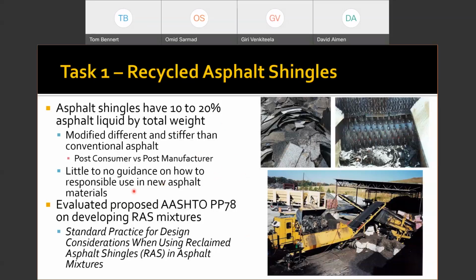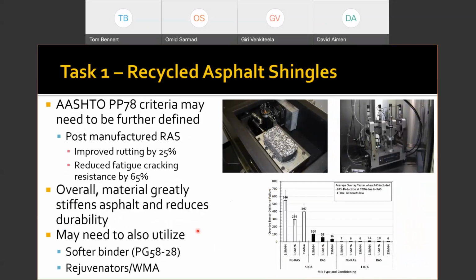And so we went back, took a look, did a research study looking at this proposed AASHTO method that they were proposing. And again, the idea here is, can we actually responsibly use recycled asphalt shingles in new hot mix asphalt? And we looked at a surface mix, we looked at a base course mix, could we put it deeper in the structure? We looked at the rutting, we looked at the cracking, and what we found was that the stiffer binder improved the rutting resistance, but it promoted cracking. And it promoted cracking to the extent where it really wasn't even close to our conventional type mixes.